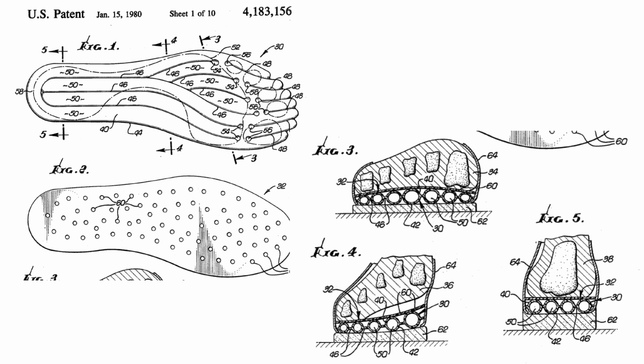The material from which the inflated insole 30 is constructed should have the following properties. 1. The material should be non-porous such that there are no pinholes, and such that the transport of the fluid which fills the chambers 50 through the material of the insole 30 is restricted to the process of activated diffusion. 2. The material should be elastomeric and capable of stretching within controlled limits to form a complex compound geometric shape without folds and wrinkles.